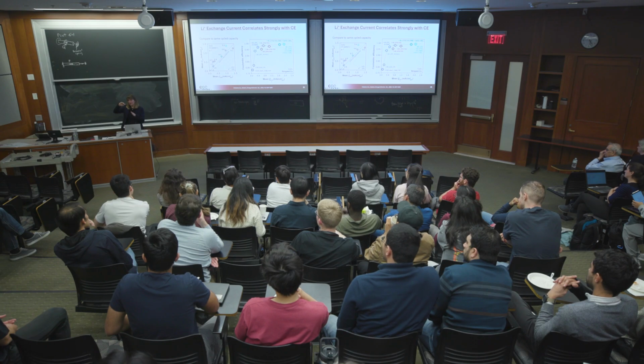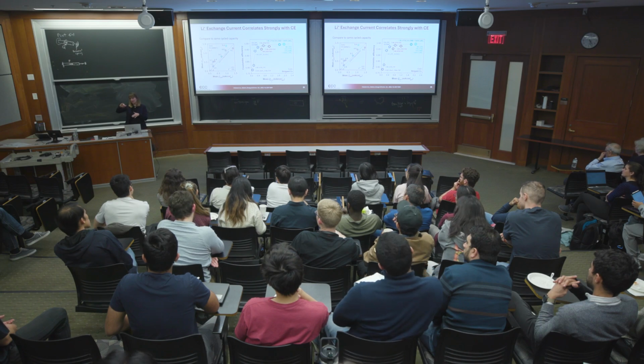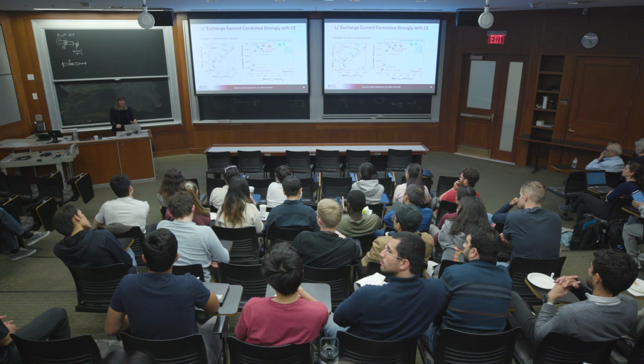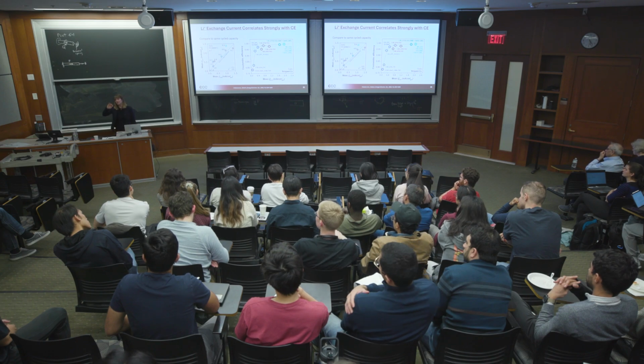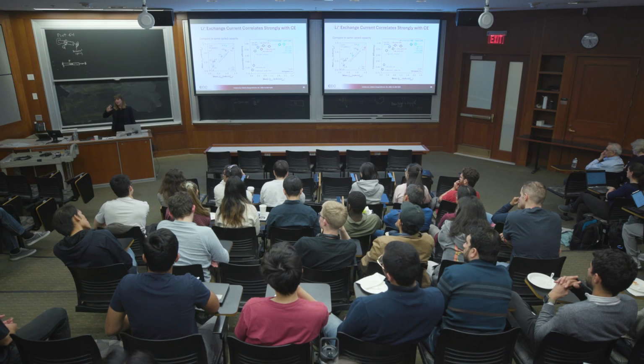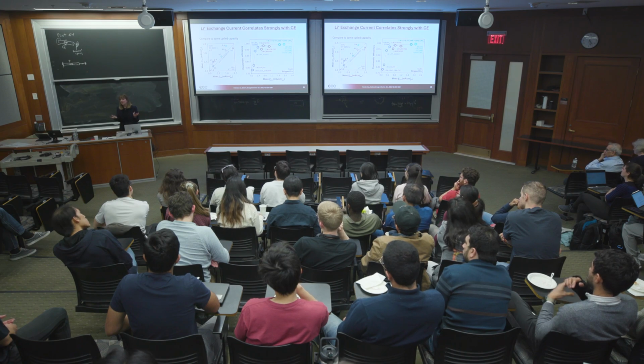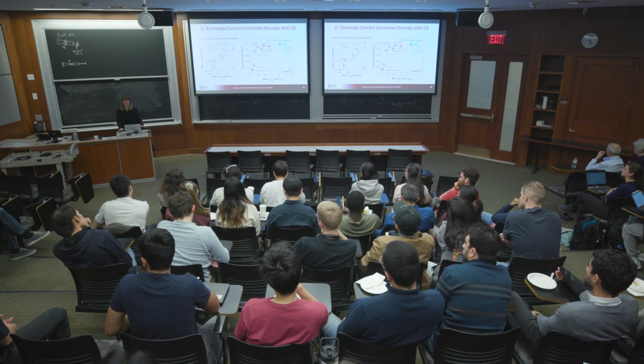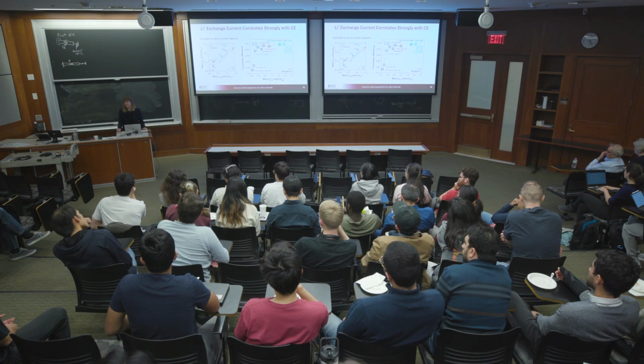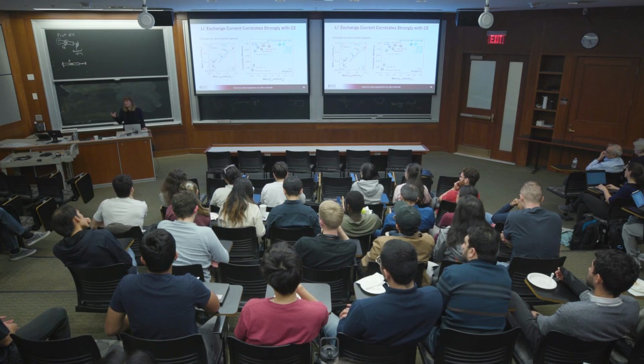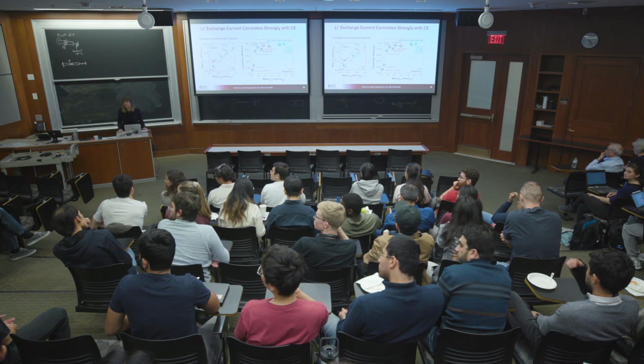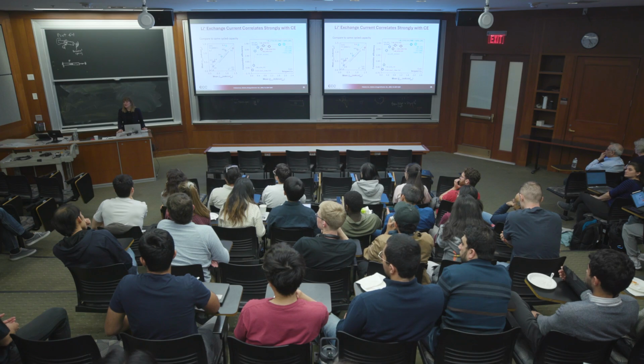We'd have to dig into the CVs to tell, but the way that we get the J naught from CVs is we do a Tafel analysis. So we actually do a linear fit, and we look at the intercept with the potential axis, and the current axis, to get what the exchange rate would be when projected at equilibrium. There are associated overpotentials with that plating and stripping. They're not too high. I don't know off the top of my head what they are, but they're typical values. They're not outrageous. For the impedance measurements, those are done at rest. So we plate and strip normally, but then the cell is resting, so there's no overpotential to speak of. So you're fitting with both of them, the linear reading? Yeah, we're doing Tafel analysis from the CVs.